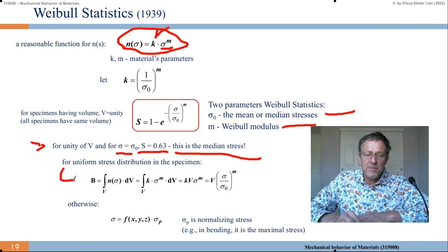For the uniform stress distribution in the specimen, we get now B equals this integral over the volume. We have had that n of sigma, so it's stress distribution dV. And we put that in, n of sigma here from the top, k times sigma to the m dV, and that we can solve: equals k times V sigma to the m equals V times sigma over sigma 0 to the m.